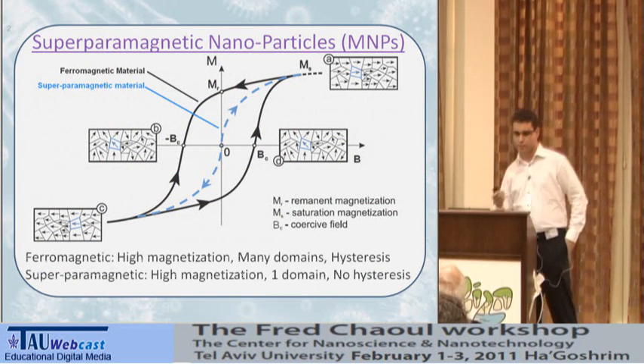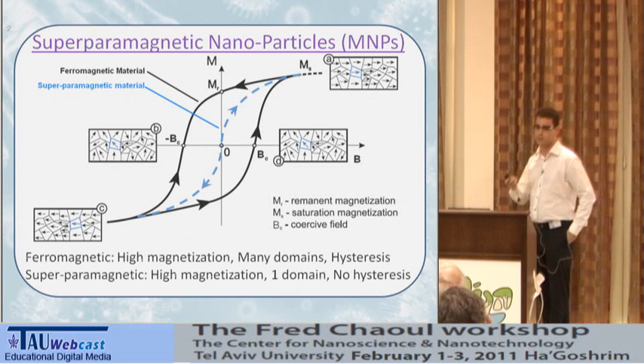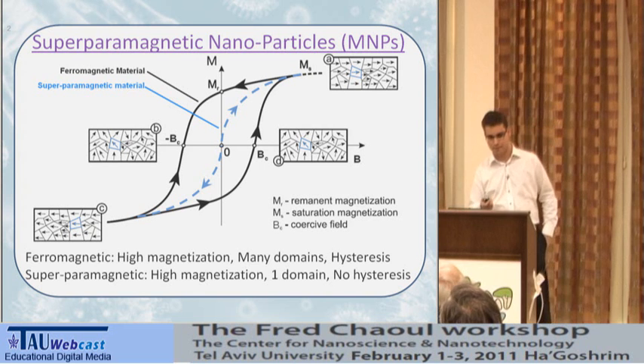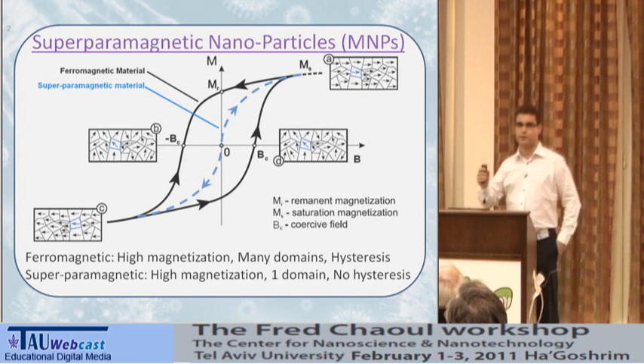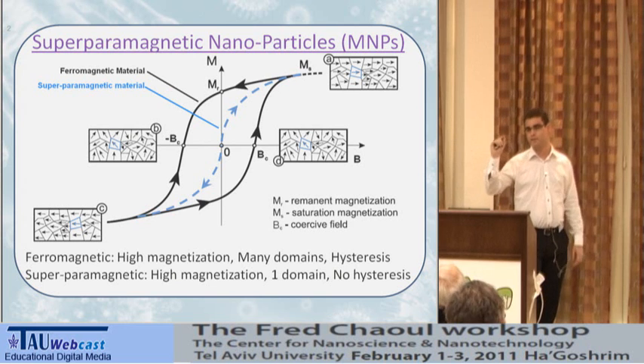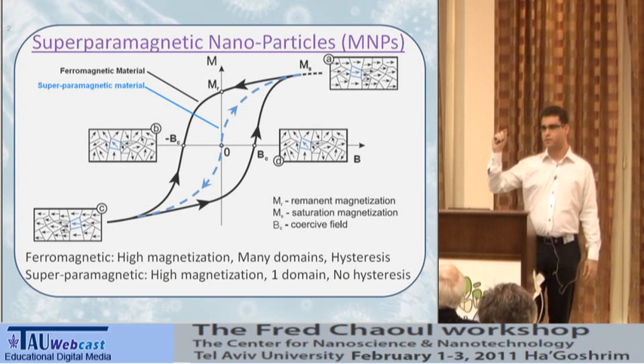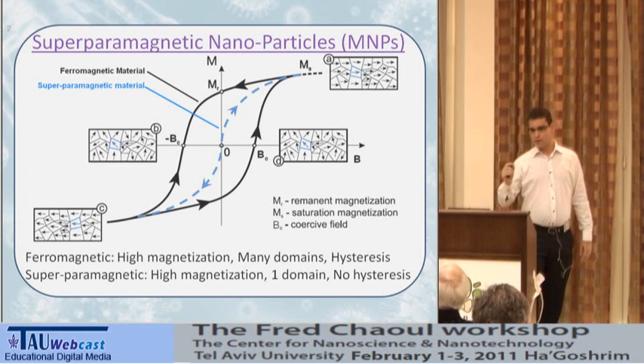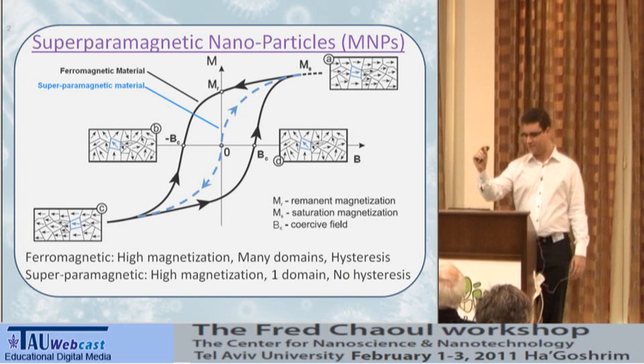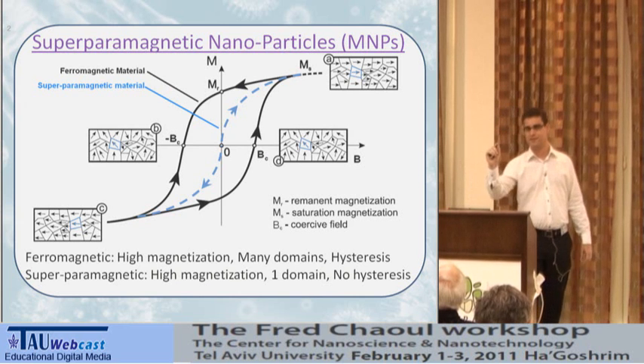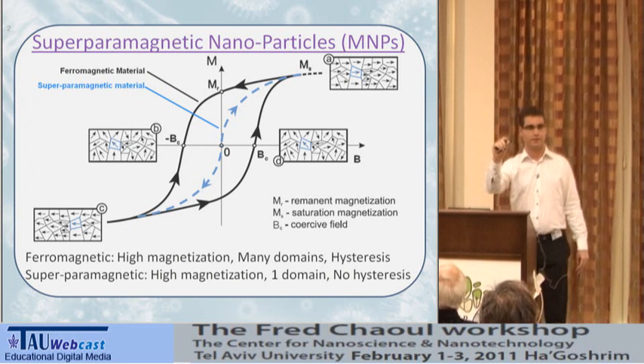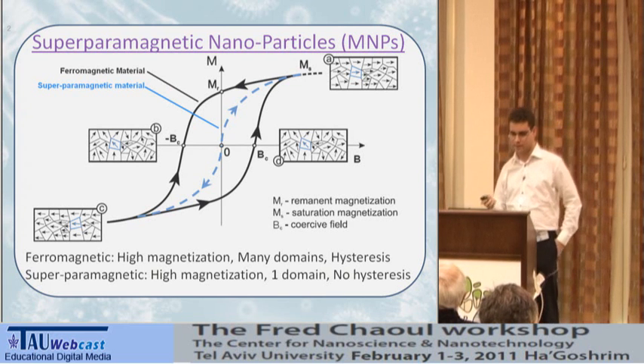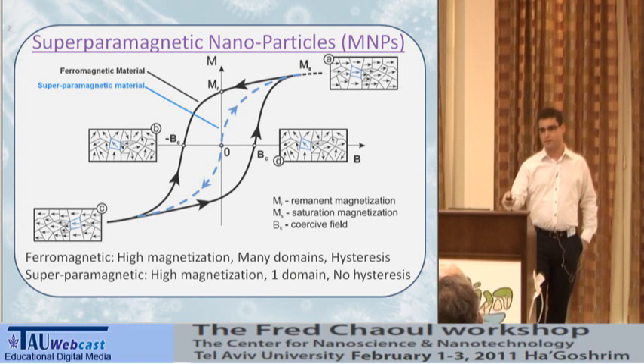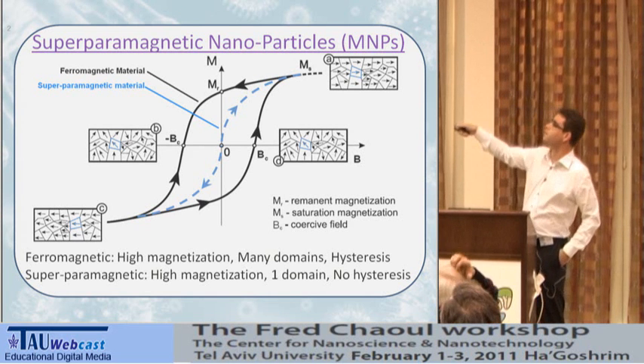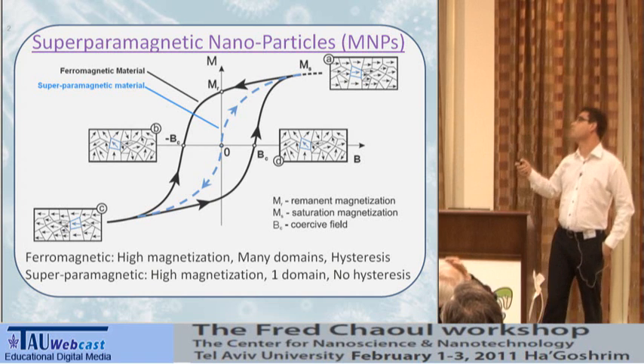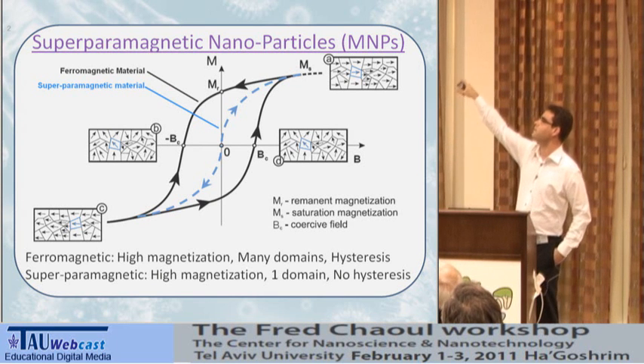So basically, we're using superparamagnetic nanoparticles. What are these superparamagnetic materials? If you take ferromagnetic materials, you can see it is composed of many isolated magnetic domains. Each has its own magnetic moment. If I take just one tiny piece out of the ferromagnetic material, I get a single magnetic domain, and that's what we call a superparamagnetic nanoparticle. So a superparamagnetic nanoparticle won't have the hysteresis curve like a ferromagnetic matter has, just the saturation curve.